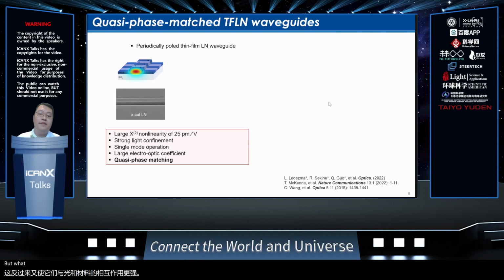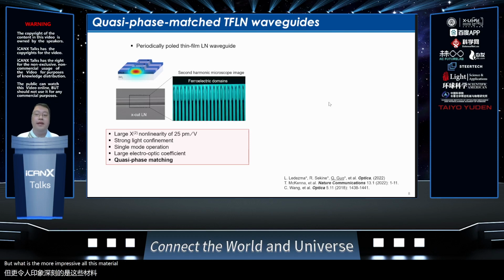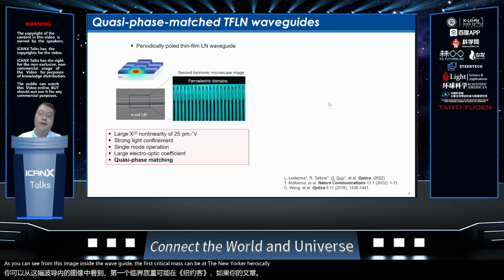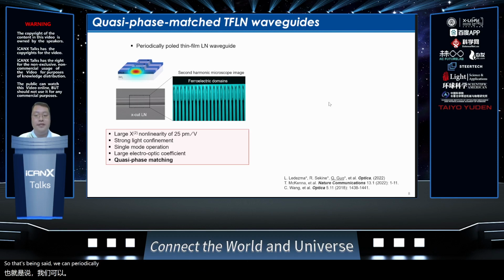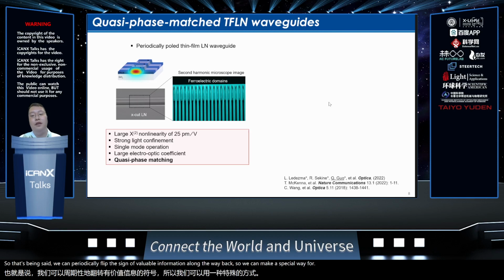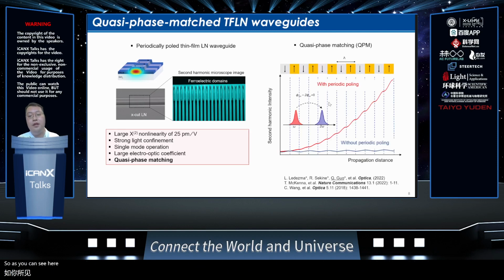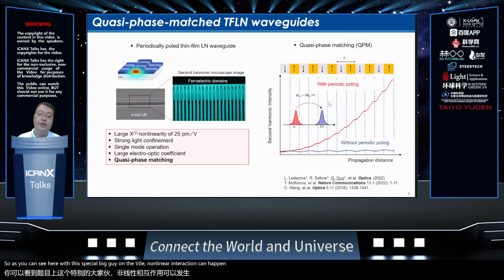But what is even more impressive about this material is that lithium niobate is also a ferroelectric material. As you can see from this image, inside the waveguide, the ferroelectric domains can be engineered periodically. That is, we can periodically flip the sign of the nonlinear coefficient along the waveguide. So we can make a special waveguide called the periodically poled lithium niobate waveguide. With this special waveguide, the Chi2 nonlinear interaction can happen continuously and strongly without any back conversion. This is a technique called quasi-phase matching.